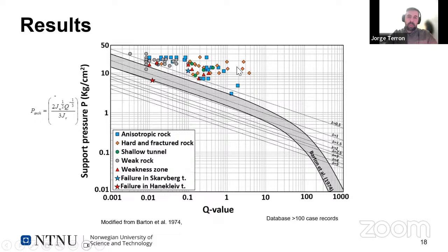And we actually see a similar tendency as we saw in the numerical approach. For example, in this case, from 0.01 to actually Q value 2 and 3, the rock support pressure of the installed support is very much above and increasing towards the right-hand side of the graph. So at some point in this empirical graph, we have a mismatch with the numerical calculations where we say it's 0.1, but it's also clearly indicating that we are using too conservative design in Norway.